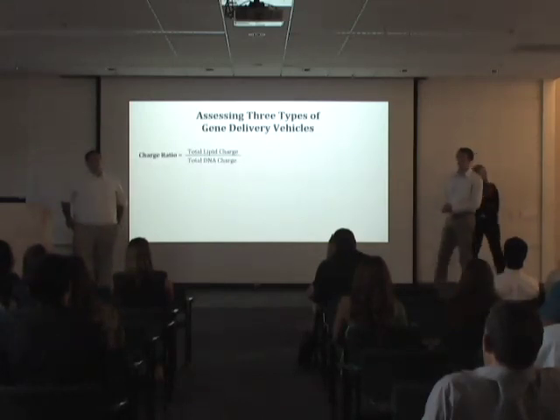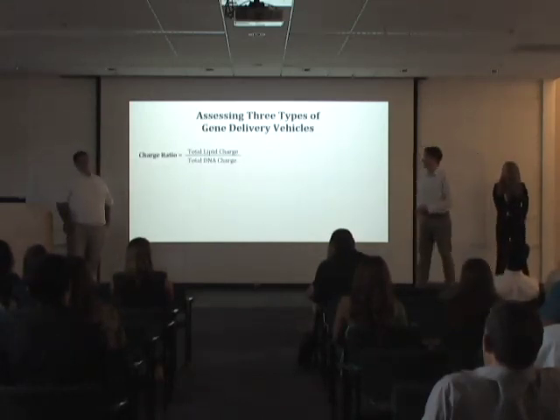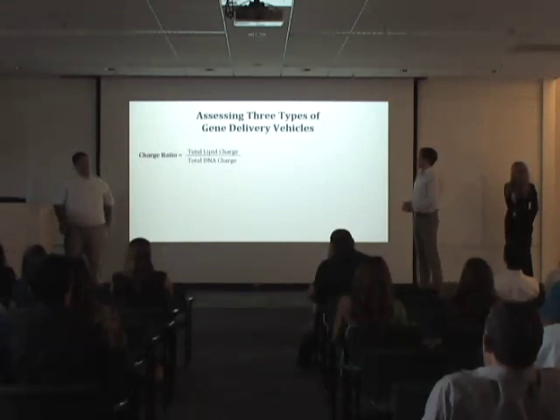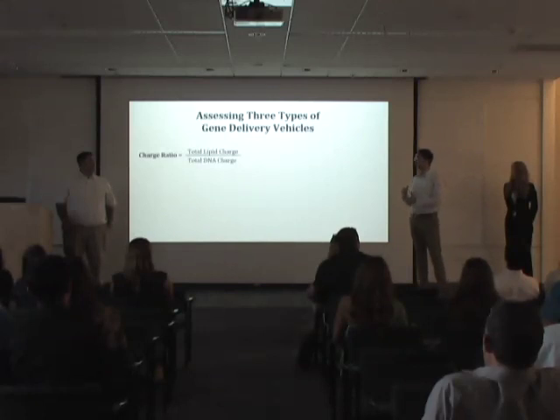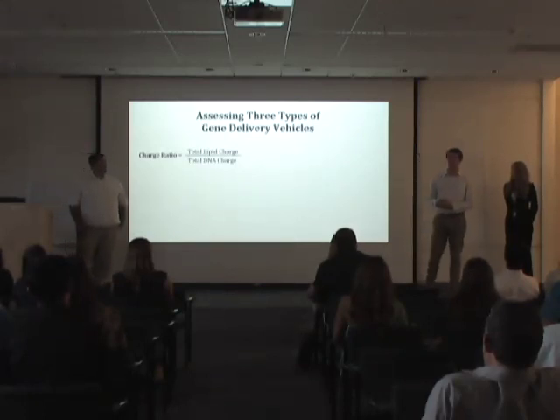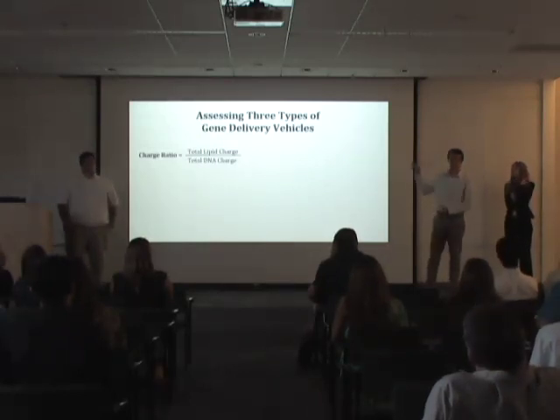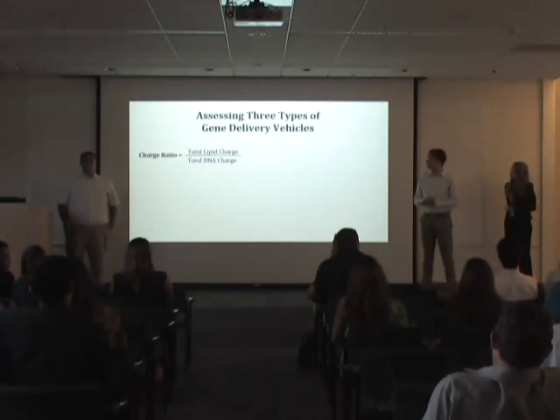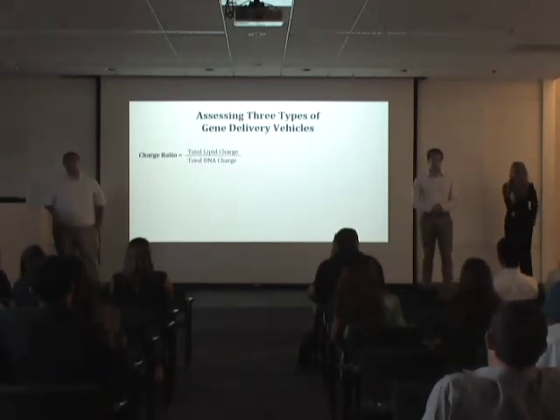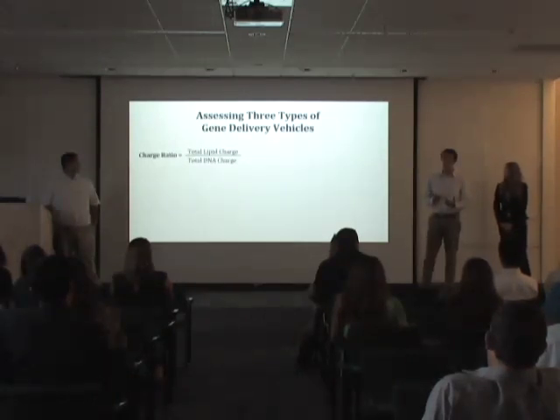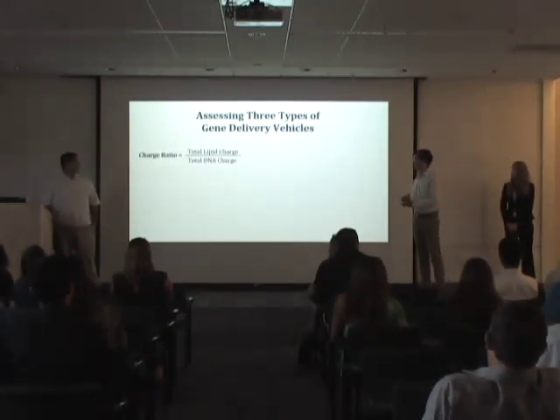As for the three different gene delivery vehicles we will be using, we have mixed each one with a positively charged lipid. This is important because cells and DNA are mostly negatively charged, and we have designated a charge ratio to each one of our lipid nanoparticles. Charge ratio takes into consideration the total lipid charge over the total plasmid DNA charge. This way we can get an idea of how a lipid nanoparticle will interact with the surface of the cell.